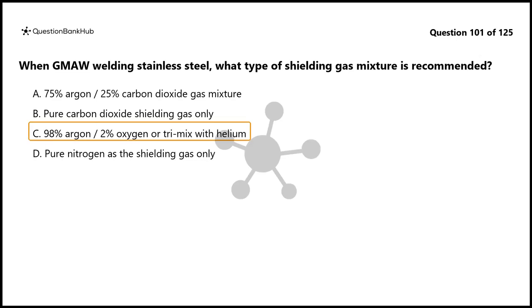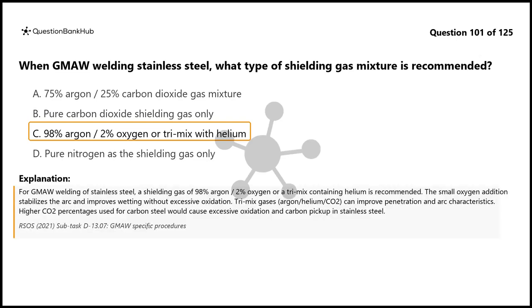The correct answer is C. 98% argon over 2% oxygen or trimix with helium. For GMAW welding of stainless steel, a shielding gas of 98% argon over 2% oxygen or a trimix containing helium is recommended. The small oxygen addition stabilizes the arc and improves wetting without excessive oxidation.